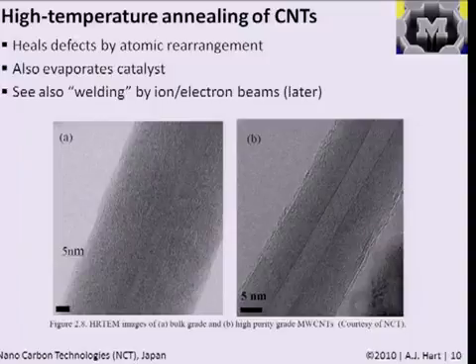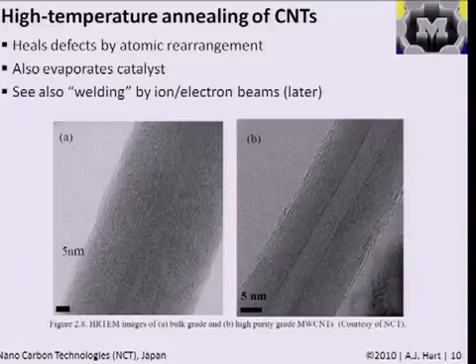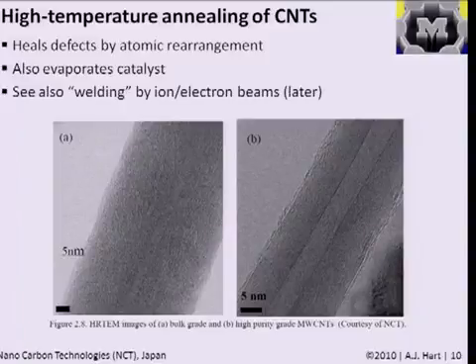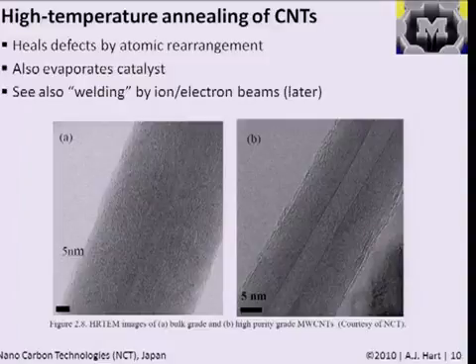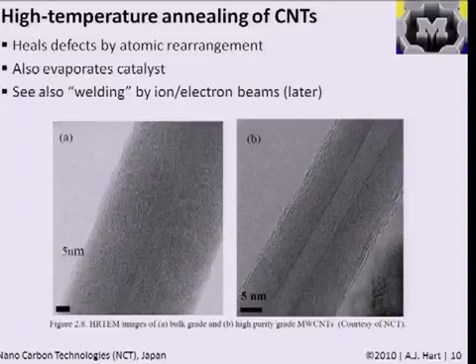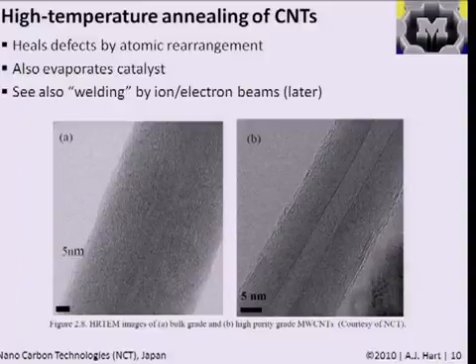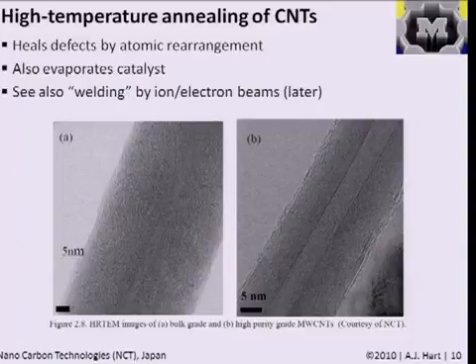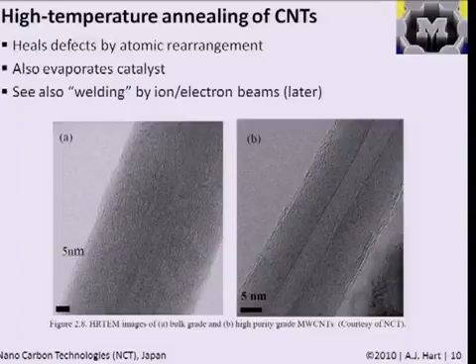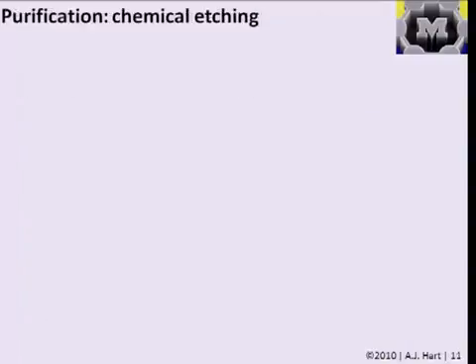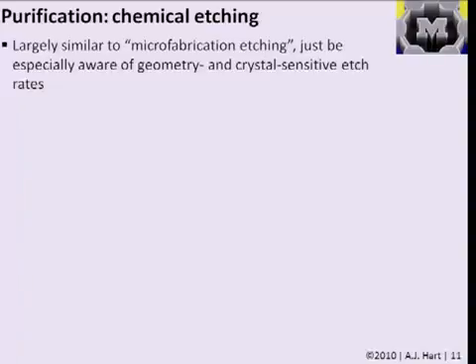You can see this change by looking at thermal decomposition temperature, diffraction, or Raman spectroscopy — it's clear that the organization of the walls is much better after annealing. So even if CVD processes inherently produce defective structures, it's possible to scalably treat the material to reach a better state. These tubes are quite structurally good for producing multi-walled tubes in large quantities — this large-scale process is pretty much a solved problem. In the annealing process, they also remove the catalyst by evaporation, since the melting temperature of iron is far below that of carbon.